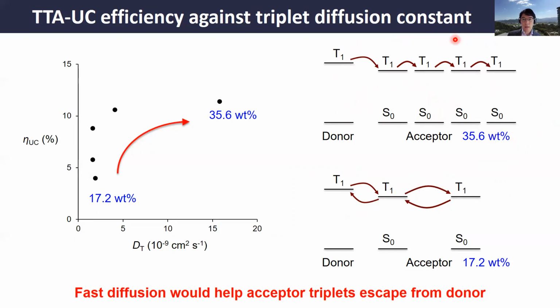Okay, so an acceptor concentration above 38% in such an amorphous, rigid network is very important. If you have such a high concentration, you can get nice upconversion even in the rigid film without molecular diffusion.